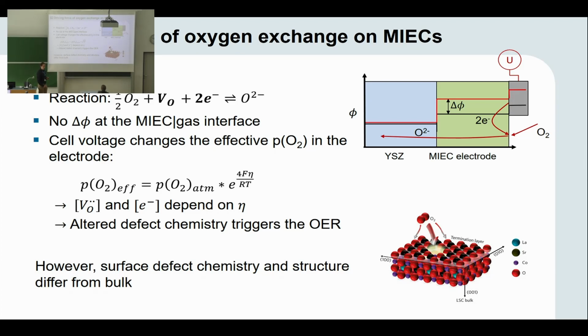Normally in electrochemistry, you would think you have some potential in your different phases, and when you switch on a cell voltage, you change these potentials, you get a potential step. And in most liquid electrochemical devices, the highest potential step is actually where your rate limiting process is located. However, in SOFCs, the rate limiting process is at the solid gas interface. And since the gas phase is an insulator, there is no defined potential step at the solid gas interface. So on first sight, it's actually a bit puzzling what is actually driving the electrochemical reaction.